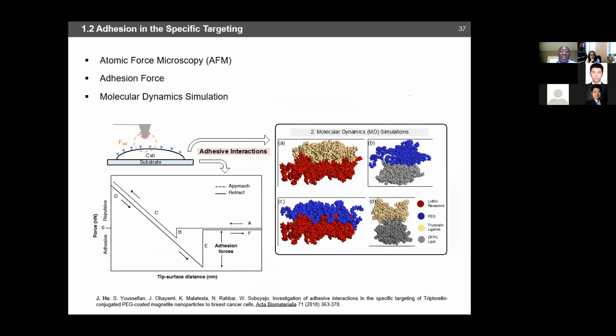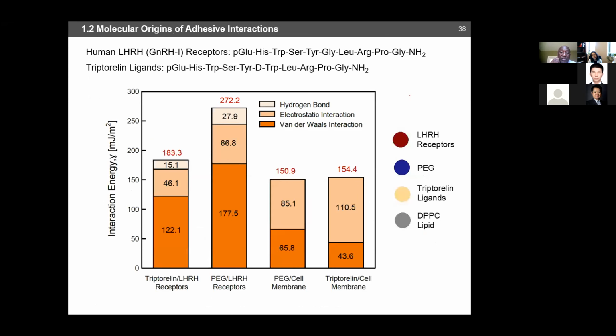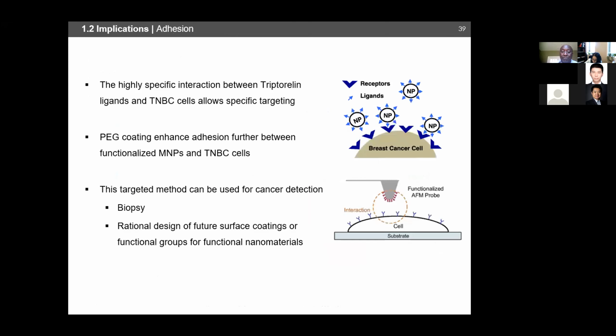Now, to begin to understand this, we've done molecular dynamic simulations here, working collaboratively with Nima Rahbar, who is a professor at WPI, and his student, Avan Navabi. And what we basically have shown is that the adhesive interactions are associated with electrostatic interactions and van der Waals interactions with relatively small contributions from hydrogen bonds. And these adhesive interactions explain the specific nature of the interactions between the LHRH and the breast cancer cells.